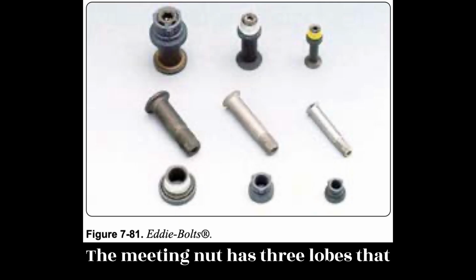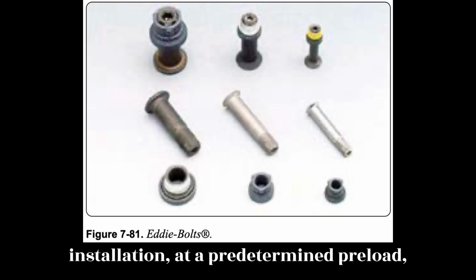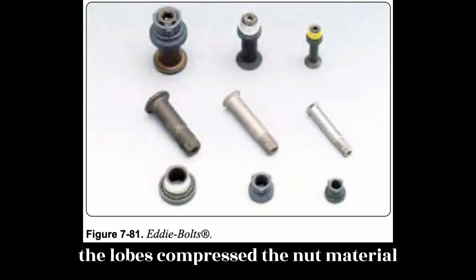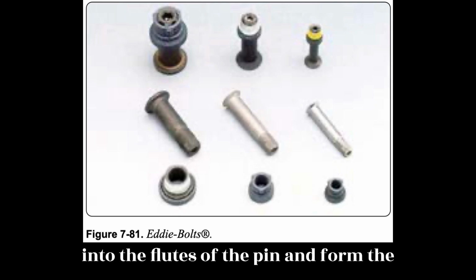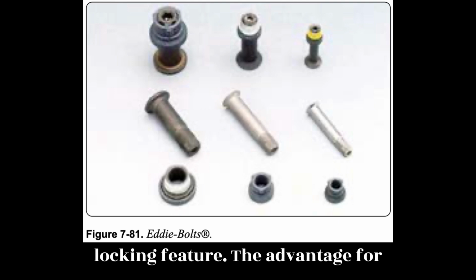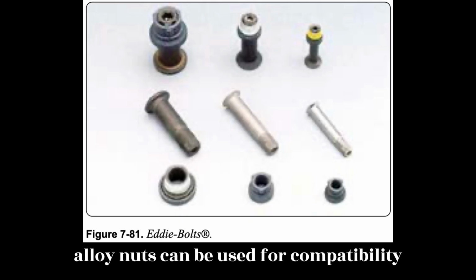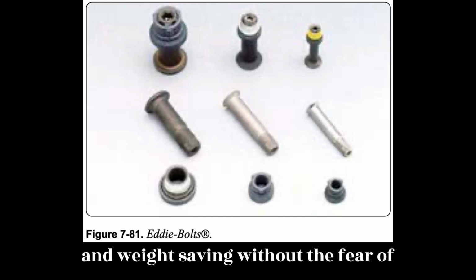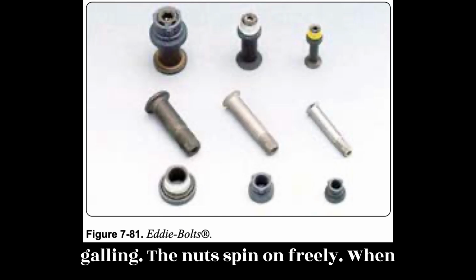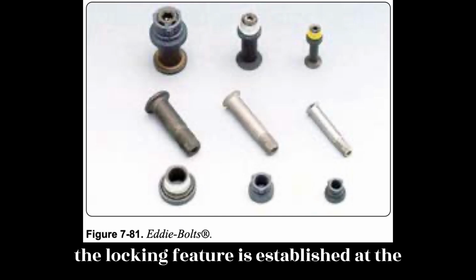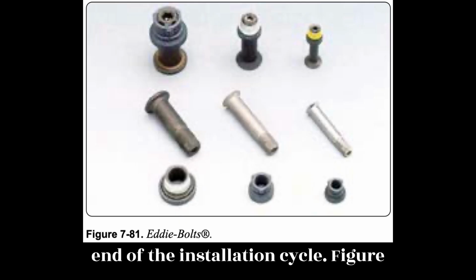The mating nut has 3 lobes that serve as driving ribs. During installation, at a predetermined preload, the lobes compress the nut material into the flutes of the pin and form the locking feature. The advantage for composite structure is that titanium alloy nuts can be used for compatibility and weight saving without the fear of galling. The nuts spin on freely, and the locking feature is established at the end of the installation cycle.